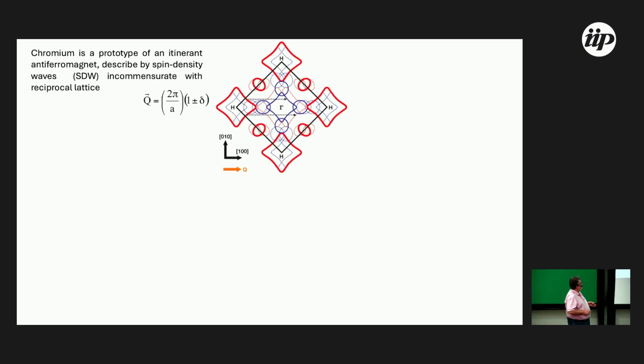So chromium is a prototype of the itinerant antiferromagnet described by spin density waves. And these spin density waves are incommensurate with the reciprocal lattice. This is the first special point about chromium. The magnetic order is different from the lattice. The Q vector characteristic of the spin density wave is 2π/a in reciprocal space, times 1 minus or plus delta. And this delta depends on the temperature and on the characteristics of the alloy.